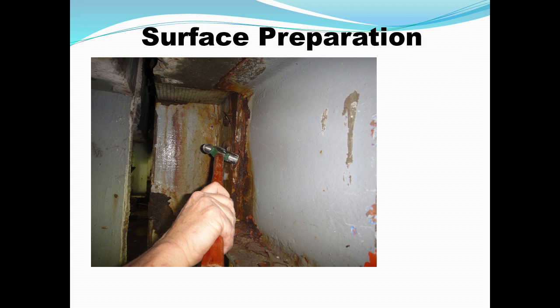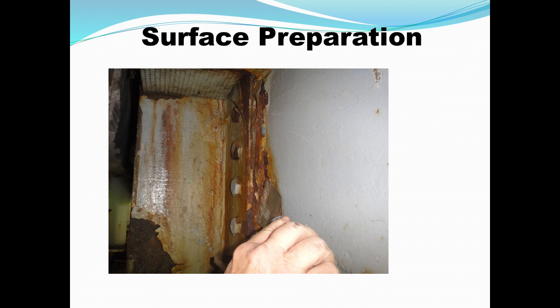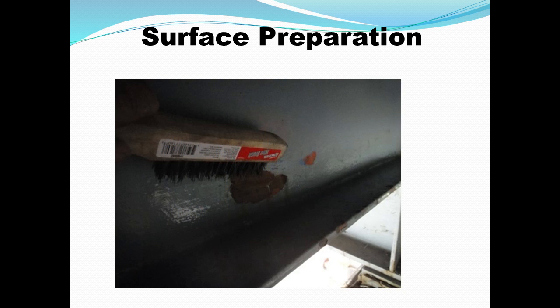I've seen it abrasive blasted and remained there, but an impact does a really good job of popping it off. So any of the areas that had some stratified rust, we would pop it off with an impact, use a hammer. Then we scraped the areas to remove all the loose paint and corrosion product that we could. Wire brushed it. This is all SP2 type hand work.